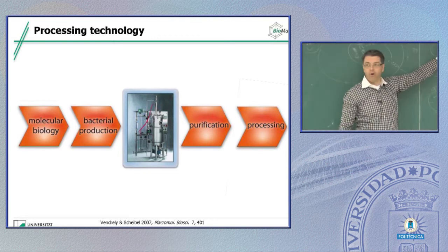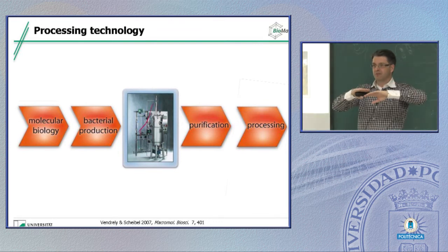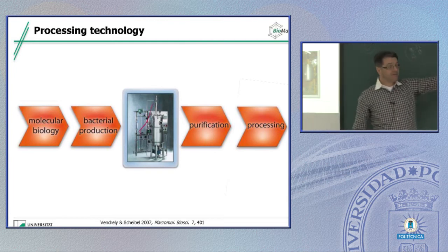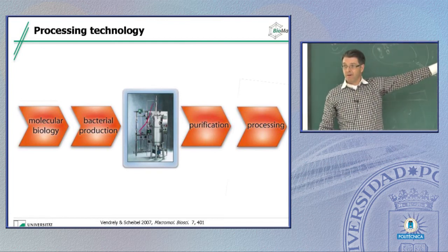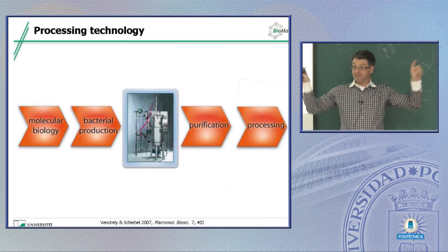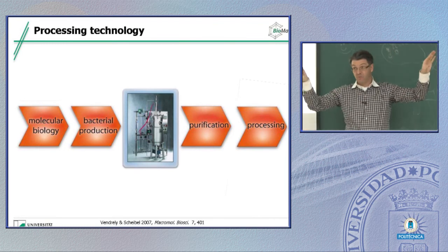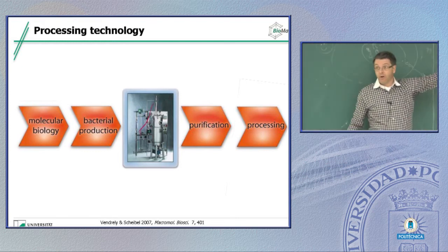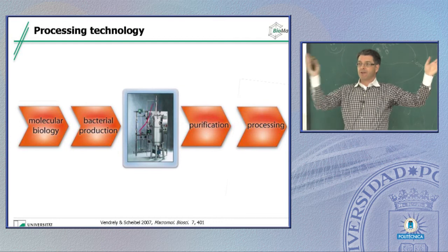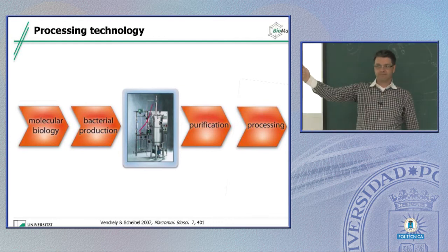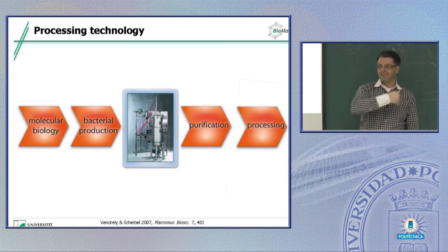And that happens with the bacterial proteins. So if you boil the whole thing, all the bacterial proteins will unfold and aggregate. The silk proteins are already unfolded, remember? There's not much that can be exposed there besides the terminal regions, but they're very thermally stable. So actually, if you boil the whole thing, everything from E. coli aggregates and separates. And then you just cool it down and take the supernatant, and there you have the soluble silk.